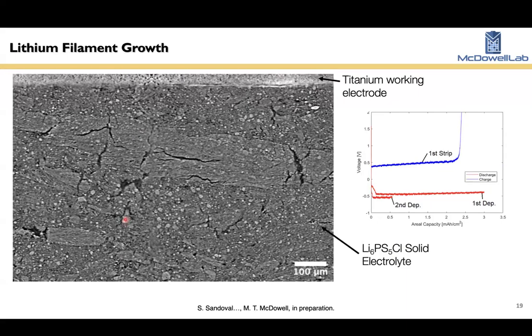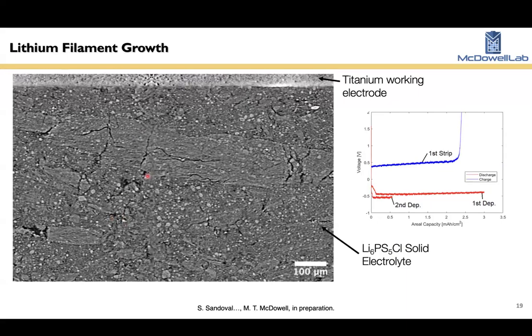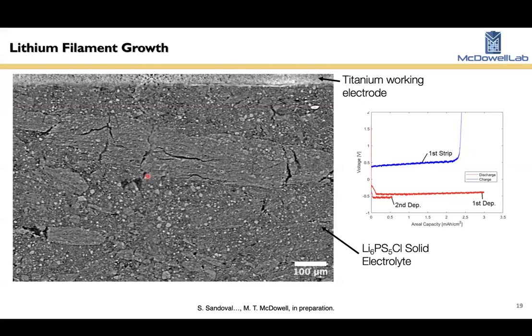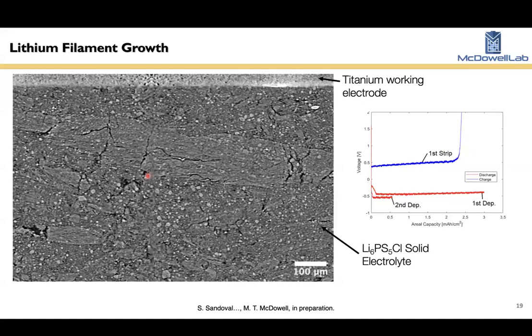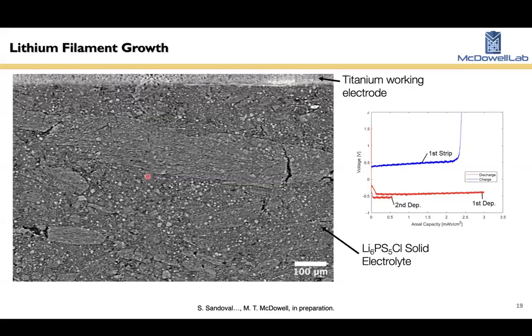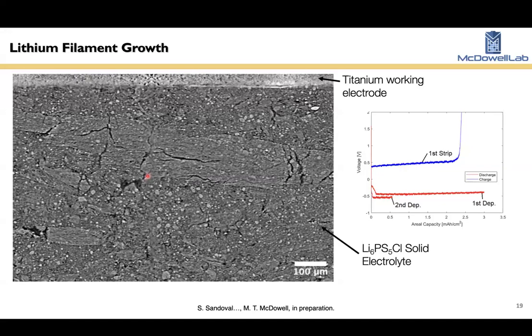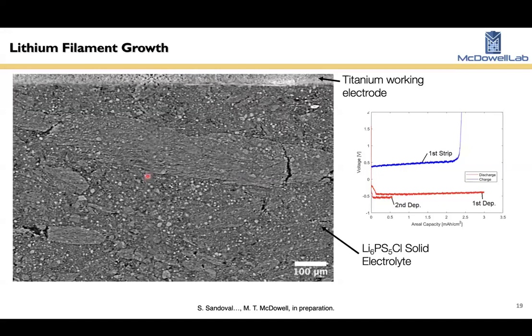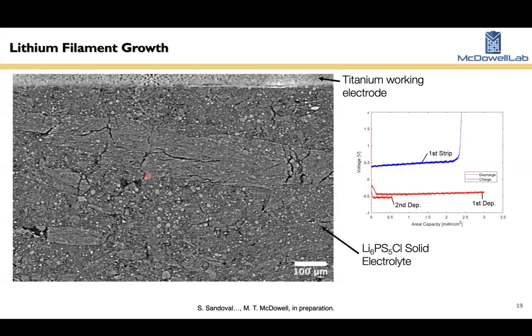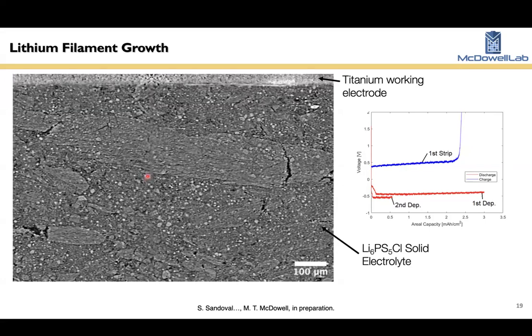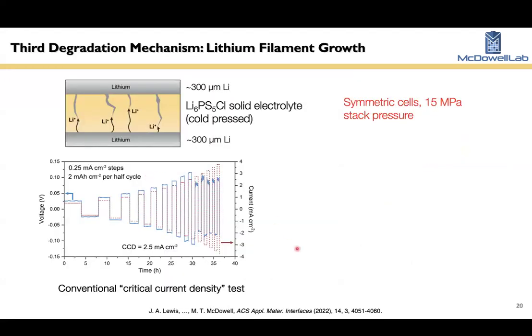I think that the general state of understanding in the field is that this is truly a mechanics process. There's stresses that are evolved near the crack tip due to lithium growth. Lithium is under high compressive stresses in these cracks, and it basically forces itself and causes these cracks to propagate through the solid electrolyte. We have a paper that was published a year and a half ago or so, focused on understanding lithium filament growth.